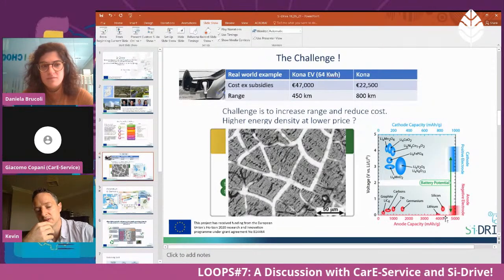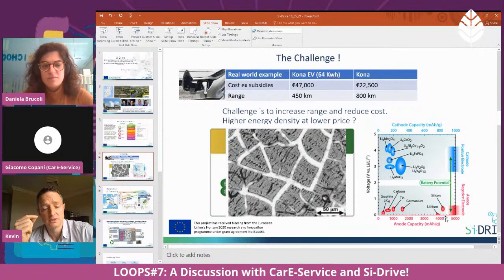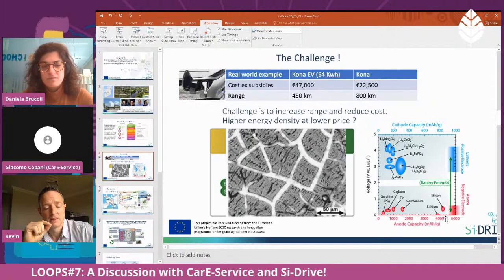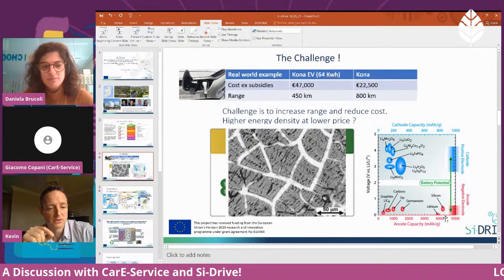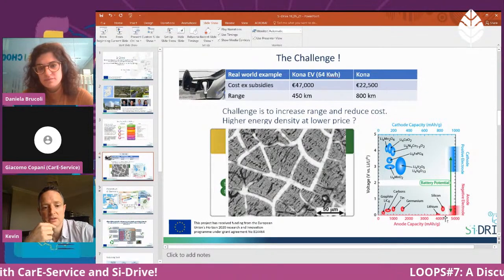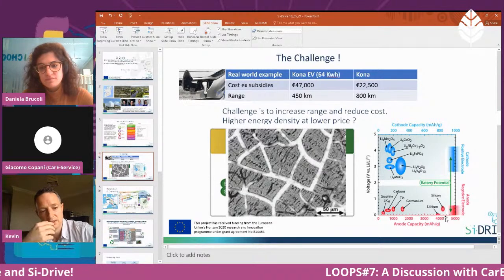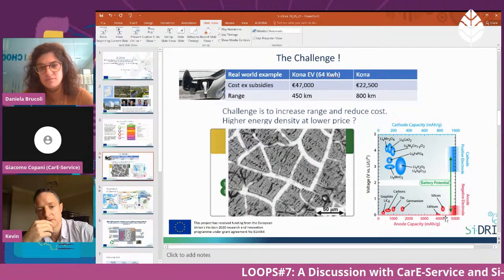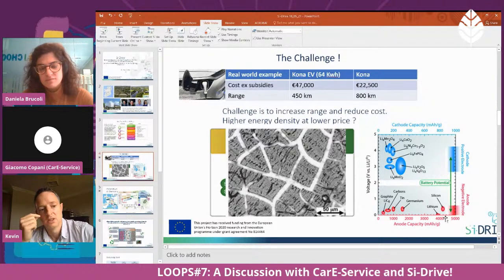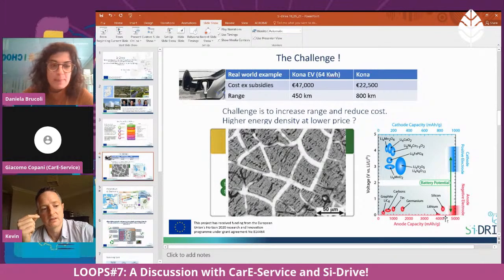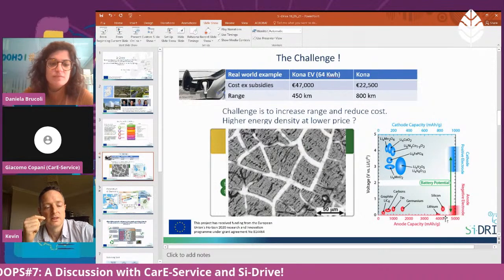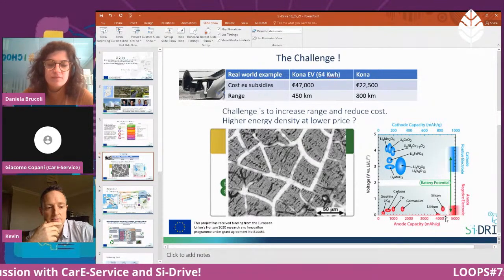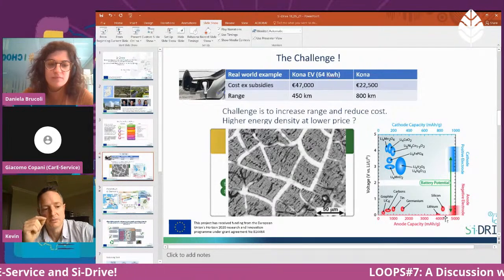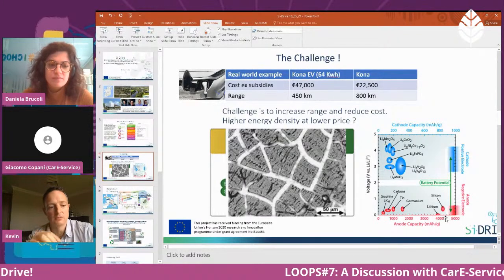we get a 300% volume increase with silicon. Now, if you were just to do this with a bulk piece of silicon similar to the size of a graphite flake, it would shatter. And this is the image that I'm showing here, which is one of these overlaid images. So we actually have to develop silicon in a different form so that it is stable. And we do this by using silicon in a nano form.